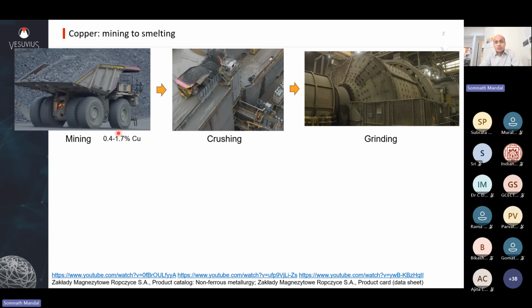Your copper ore, which is mined either from underground or open pit mines, has a world average of 0.5% copper, and Poland has about 1.7% copper. So you see, it's very low in copper content. So the challenge is very high to purify it to 99.99% purity.